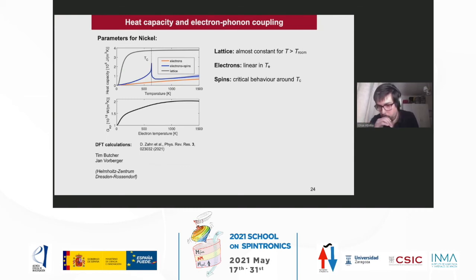The electron-phonon coupling is not constant, but has some dependence that increases with the electron temperature. This is not general, but particular to nickel. The important point is that this is the strongest coupling parameter.